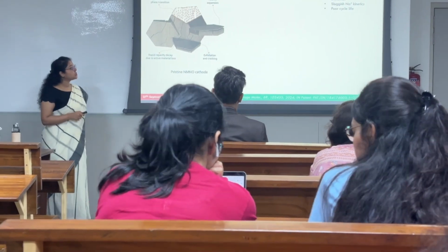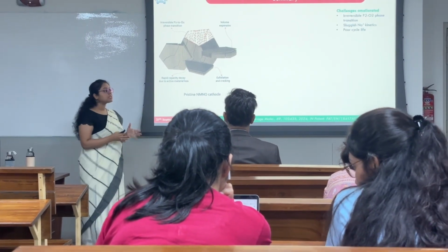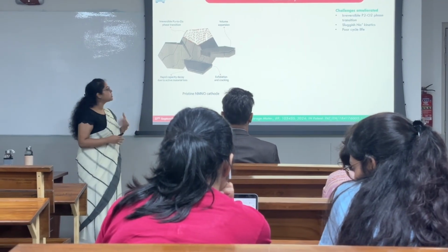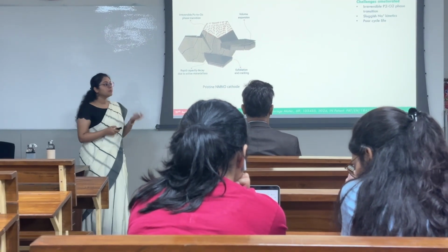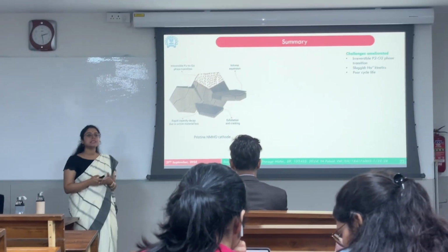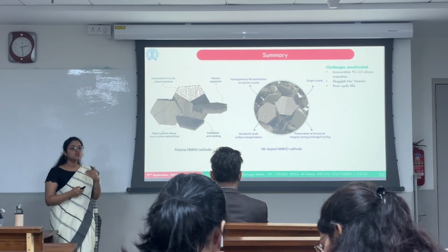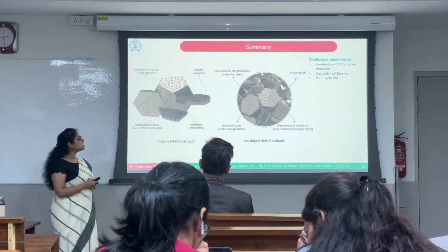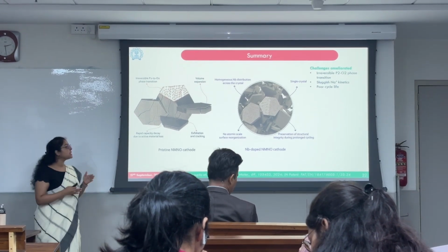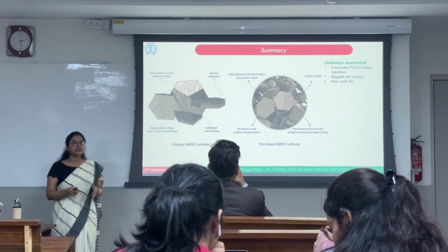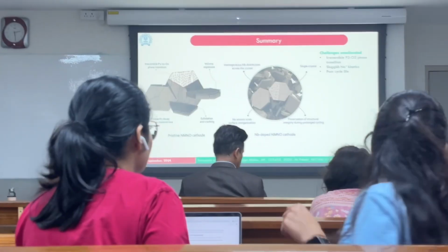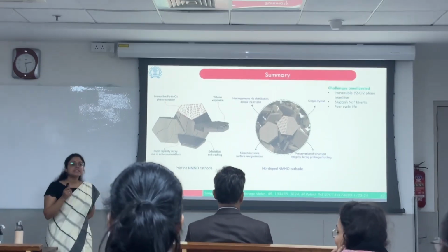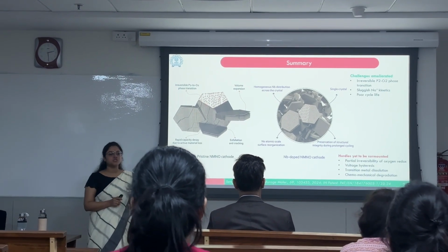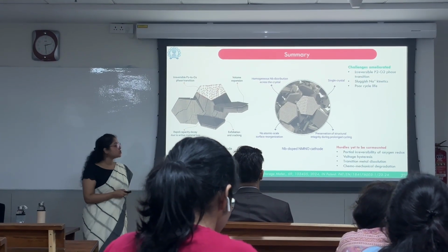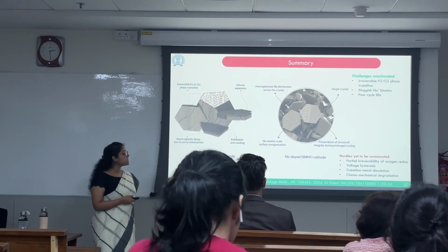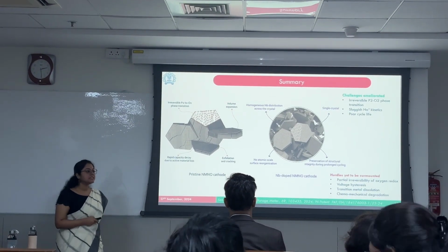Thus, in this particular chapter, we could successfully suppress the P2-O2 phase transition, in fact inhibited the formation of the O2 phase and improved the sodium ion kinetics, thereby improving the cycle life by doping niobium homogeneously across the crystal, making single crystals, and also thereby not inducing any kind of atomic scale surface reorganization and preserving the entire structure through prolonged cycling. Still, there are certain challenges that are yet to be addressed. The first one being the partial irreversibility of anionic redox reaction, the voltage hysteresis, the transition metal dissolution, and chemomechanical degradation.